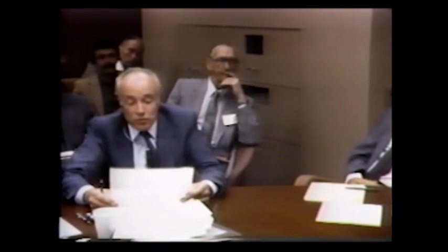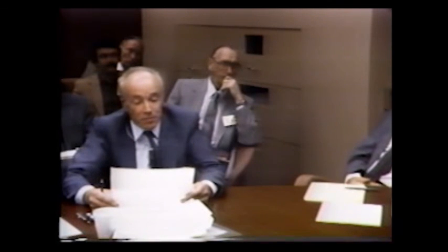Now at last, I would like to briefly discuss the situation concerning bright steel production in West Germany, which is also, incidentally, typical for Western Europe. The next figure shows the levels of bright steel production for the main West German manufacturers for 1976 to 81, in the dimensional range between 1/4 inch and 7-inch. As can be seen, production remains roughly constant, around 550 to 600 thousand tons of bright steel, with approximately 1/3 turned and 2/3 drawn.